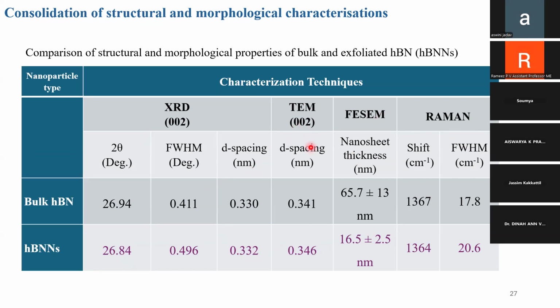In TEM you can get the d-spacing. I have already shown you a TEM image, the HR-TEM, high resolution transmission electron microscopy image, where you get the d-spacing value. I have compared it with the d-spacing I got from XRD, and you can see that it is very near to the experimental value. This way you can review what you have done experimentally against what you got in other characterization techniques. And see, this is the nanosheet thickness in bulk HBN and HBNNS, which gives you an idea that there is no crystallinity loss or structural damage in the system.